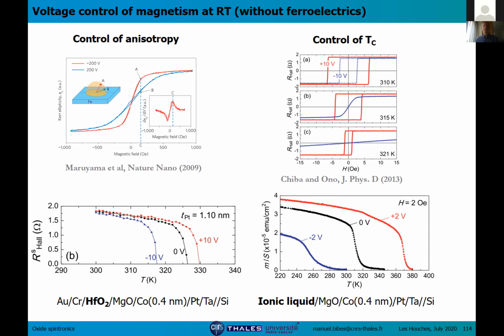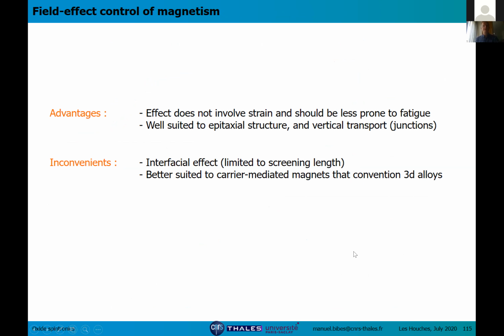And so this gives hope that you could do the same thing with ferroelectrics, but I think there's a lot of material science to do to reach this goal. So advantages of this approach: it does not involve strain, so it should be less prone to fatigue. It's well suited to epitaxial structure, so you probe really interfacial effects. So if you are dealing with vertical transport in tunnel junctions, for instance, which also probe interfacial effects, then maybe